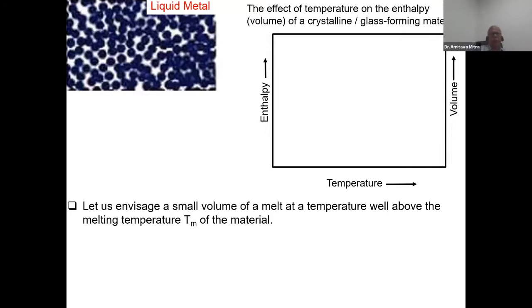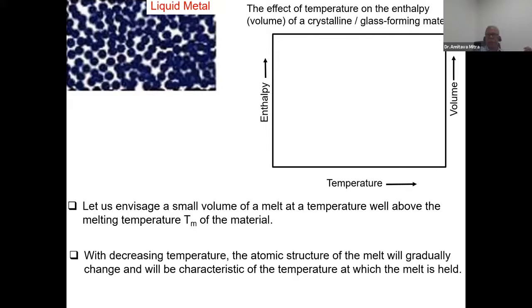For the preparations, you have to make the alloy, go to high temperature, and make the molten alloy. If you see how the enthalpy behaves after melting, you have to cool down. If you plot this enthalpy versus temperature, you will find that at the initial stage it has to be little above the melting point. Most cases we go for superheating from 50 to 100 degrees.